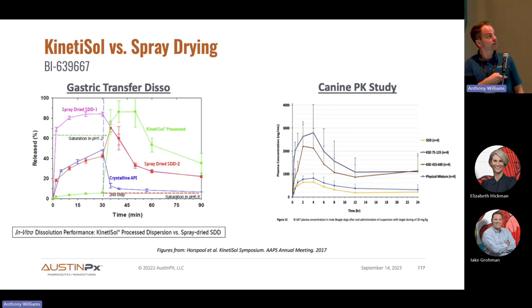So we started to form a hypothesis at this point that it's got to be something to do with the surface area or the density of the particles, that it's this protection in the acid phase that protects the amorphous payload for release in the intestinal tract, whereas with spray drying, the higher surface area particles, the drug's able to diffuse out of the enteric matrix before the polymer is soluble. So you've released your spring without deploying your parachute. But in the case of KinetiSol, your parachute is preserved until the spring releases in the neutral phase, and then you deploy them simultaneously. So to use the verbiage from the Taylor group these days, KinetiSol particles promote congruent drug polymer release, whereas in these cases, the spray dried particles seem to be promoting incongruent drug polymer release.